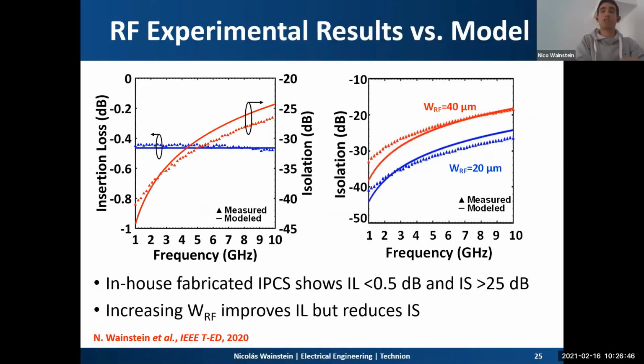The model also accurately predicts the RF performance of the IPCS. So as you can see here in the two panels, in the left panel the insertion loss and the isolation of a 20 micron device, while in the right panel, you can observe the isolation for 20 micron and 40 micron devices. The solid lines are the model performance, and the dots and triangles are the experimental measurements on the device. Also see that the insertion loss is very low. It's below half a dB, and the isolation is beyond 25 dB for this frequency band up to 10 gigahertz.